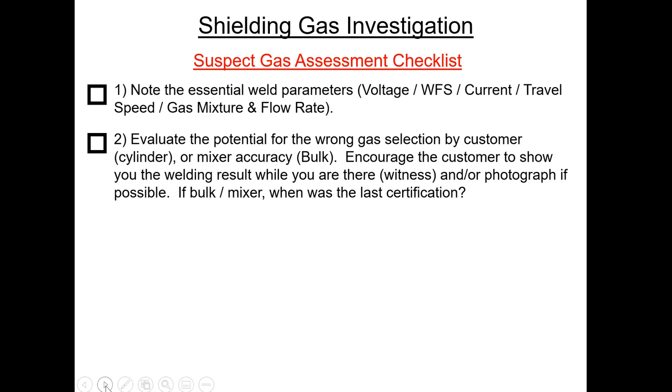Now it looks a little bit weird, there's funny waves in the weld when it's all argon. But keep in mind that the imbalance of these gases will not cause porosity. So if your mix is off, there's a bunch of other problems. But if the mix is off, it's not causing porosity.